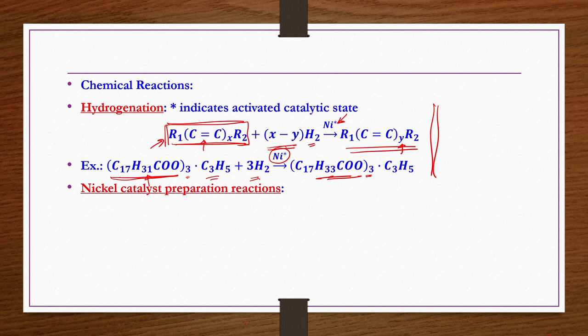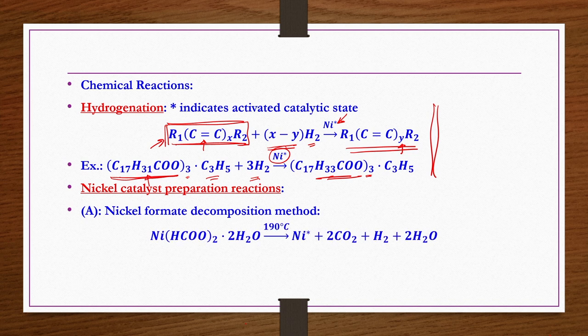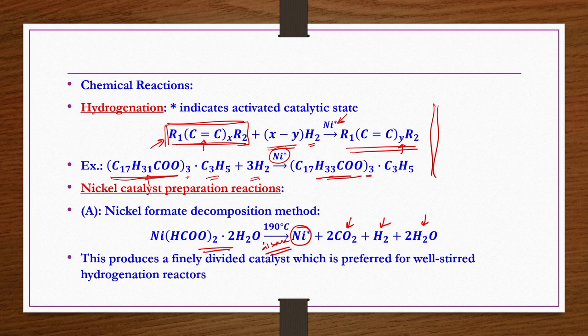Let us say if you wanted to prepare a nickel catalyst from the nickel formate decomposition, the reaction is that nickel formate, if you heat it to 190 degree centigrade in an oil bath, this is an oil bath reaction, then what happens? The carbon dioxide, hydrogen and then water vapor would be released, and then you get nickel, activated nickel catalyst having sufficiently high surface area, right. This produces finely divided catalyst which is preferred for well stirred hydrogenation reactors, ok.